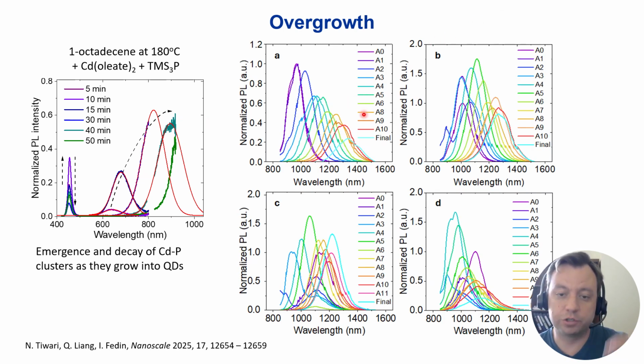Next, we used cadmium phosphide quantum dots as seeds and injected cadmium phosphide clusters there. What happened through Ostwald ripening: clusters dissolved and overgrew onto larger dots, similar to what happens in clouds. When we use small cadmium phosphide dots as seeds, we observed growth of cadmium phosphide from clusters in them. Larger cadmium phosphide dots first etched and then overgrew.